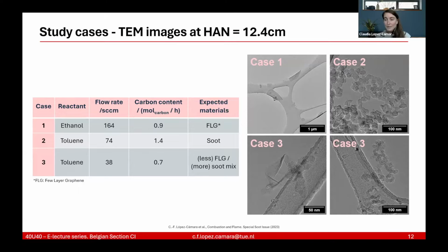In case 2, you see the soot, which was collected, which was the expectation as well. And in case 3, you can see on the left side this crumpled graphene sheet attached to the support of graphene. And on the right side, you can see also the soot that we've obtained. So we obtained a mixture of both.